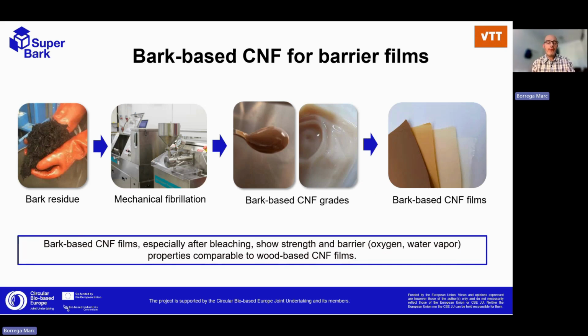This is another type of application. Rather than a coating, we have been working on using this nanocellulose to make films, for example, to replace different types of plastic packaging. We have been using bark residues with and without bleaching, because we wanted to see what the effect of this polyphenolic content is in the actual nanocellulose. From the nanocellulose, we mix it with a plasticizer, and then we do casting. After drying, we make these self-standing films that you can see there on the right. They're smooth, homogeneous and continuous.